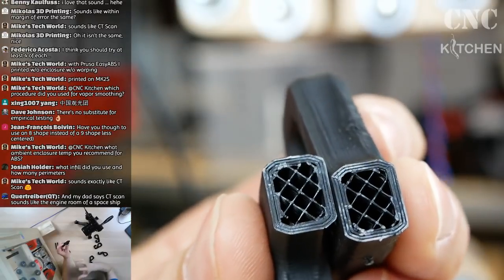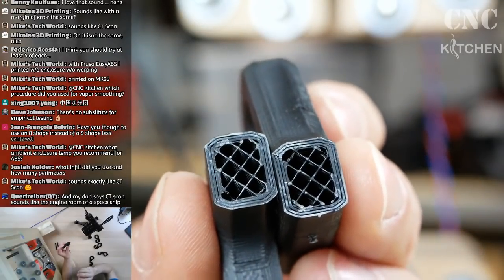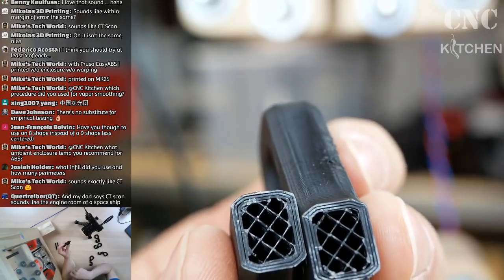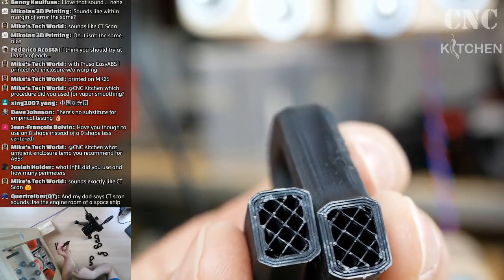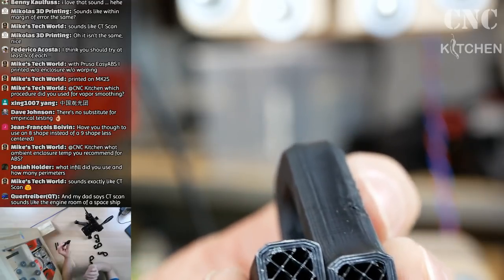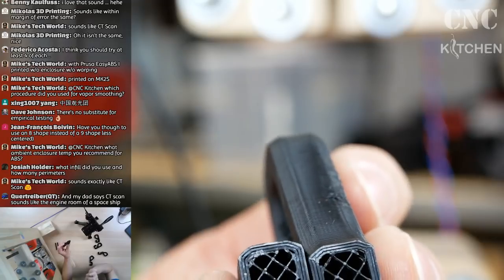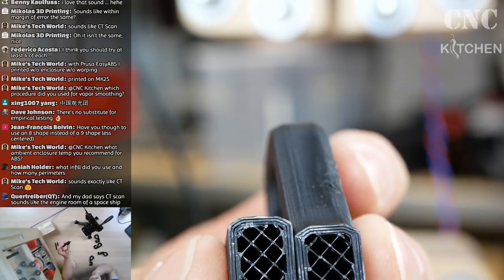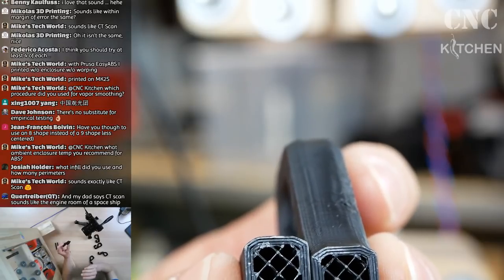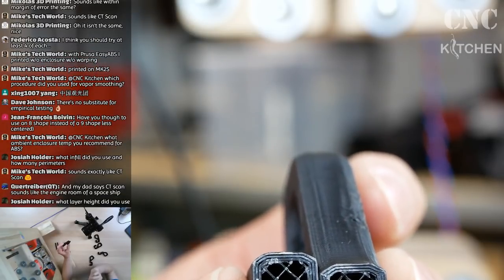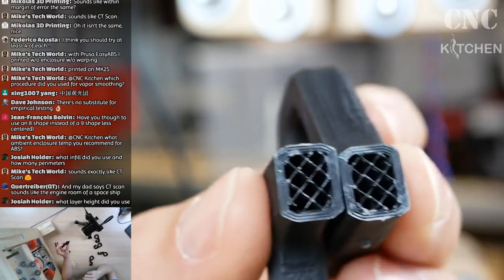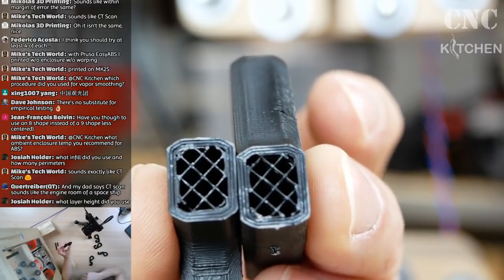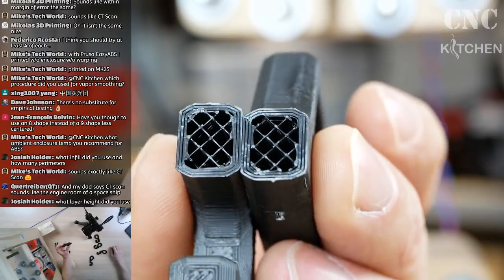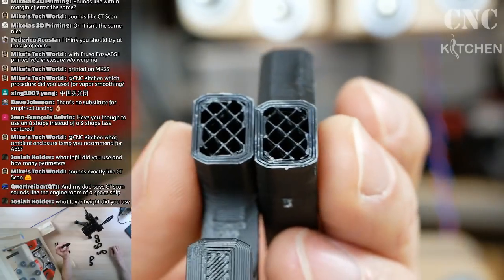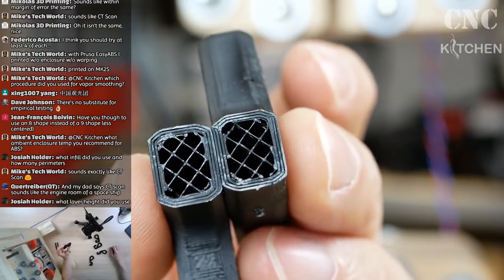But this really depends on your print settings. This depends on the material you're using. I had been using Prusa's PLA, and if you print that at 240 or 250 degrees Celsius, the layer adhesion is really good. So you get 70–80% of the strength as with a specimen which is lying down, and that's pretty cool. And this machine that I have just enables me to try out my print settings and see how they perform with the real strength of my parts.